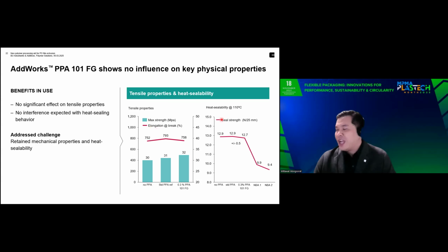For seal strength, we also conducted heat sealability testing at 110 degrees Celsius. We found no difference between our product and conventional PFAS, but we found lower seal strength values when using siloxane and modified silicone PPA.